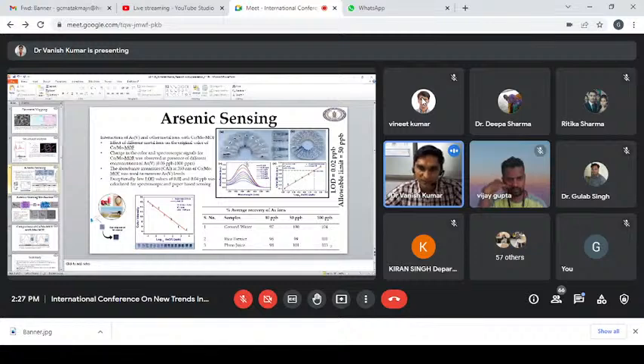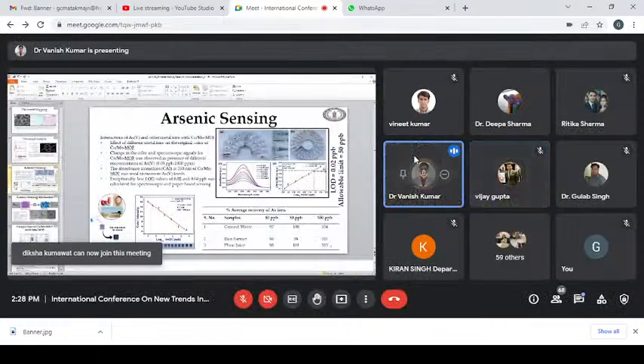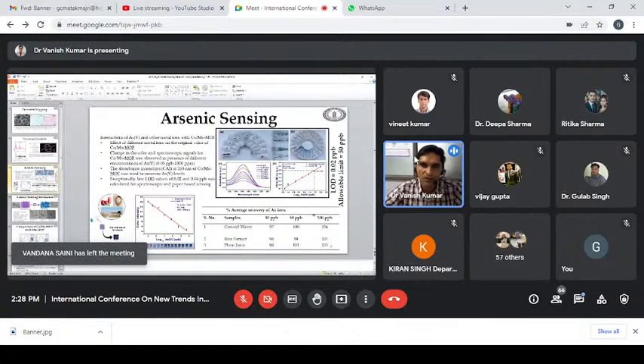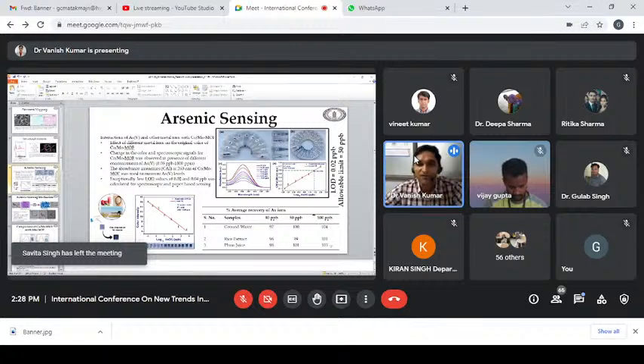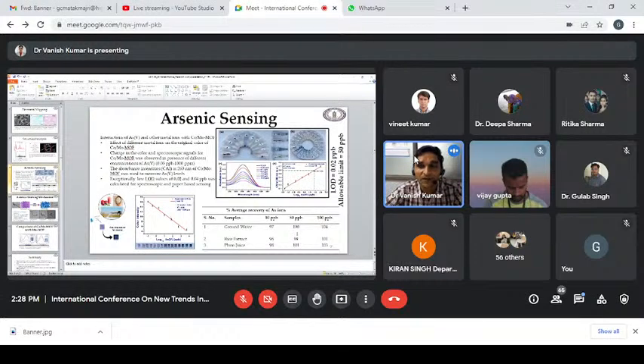After addition of arsenic into this MOF, the peak at 260 was decreased with increasing concentration of arsenic. As you see, at 0 ppb, it was around 1. At 10 ppb, it was around 0.2 absorbance. So we made a linear curve of these absorbances and found that it is linear with increasing concentration of arsenic. And when we spiked real samples like groundwater, plum juice and rice extract with a known amount of arsenic, it is giving exactly the same amount of arsenic with which we spiked that sample. We also checked the amount of arsenic in those samples with ICP-MS, and we got around 97 to 103% recovery of arsenic with our sensor.